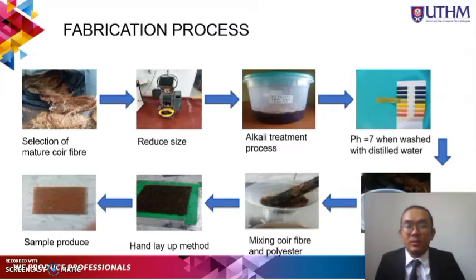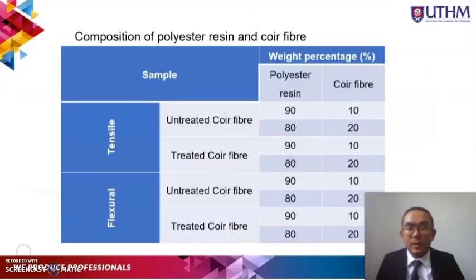This is the fabrication process. Firstly, the selection of mature coir fiber. Next, use the granulating machine to reduce the size, followed by the alkali treatment process, which is 24 hours with 5% concentration of sodium hydroxide. Then the coir fiber was washed with distilled water until the pH equals 7. Next is the drying process. After that, mixing the coir fiber and the polyester. After mixing, the hand layup method, and lastly, the sample is produced. This is the table of the composition of polyester and coir fiber.